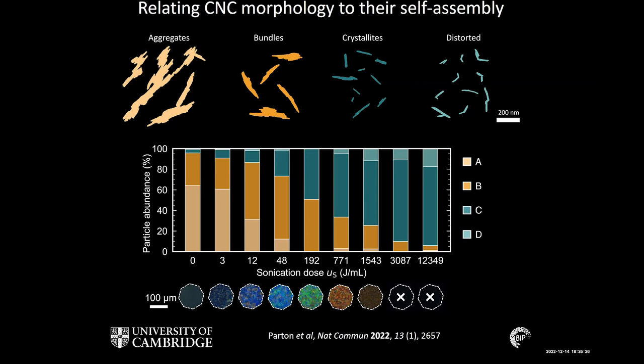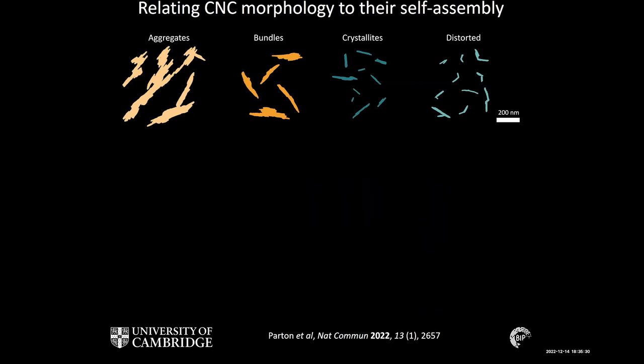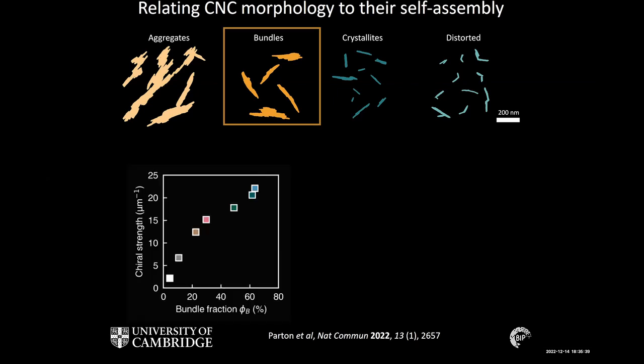And so what we noticed is that the color of the films and the strength of this twist in the suspension was strongly correlated with the relative amount of this bundle B subpopulation. In particular, here in this plot, you can see a property called the chiral strength, which is just a measure of how strongly the interactions in the suspension cause the particles to twist. And we see that this chiral strength is plotted against the relative amount of the bundle fraction. And you see that they're very clearly correlated with each other. Now, of course, correlation is not causation. It doesn't necessarily prove that these bundles are the source, but it is clear that there is a connection between the composite form of the CNCs and their assembly.